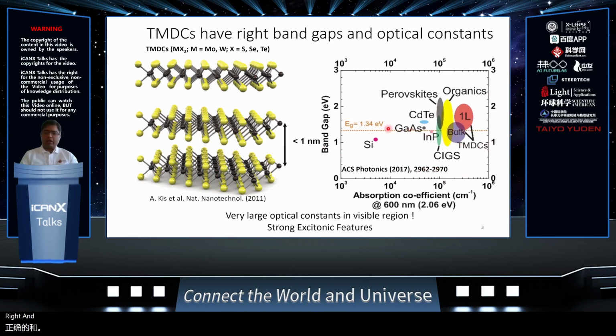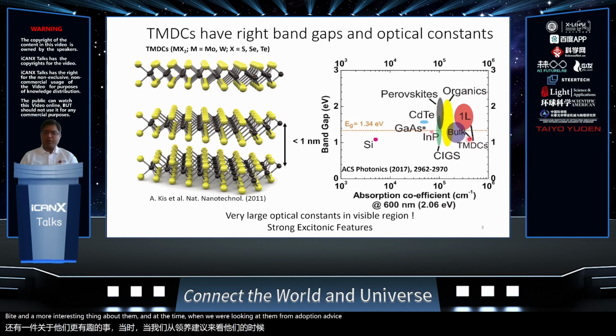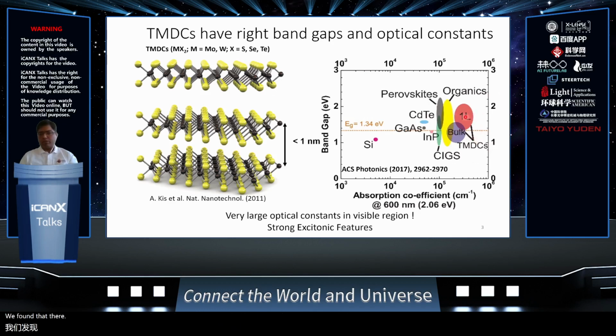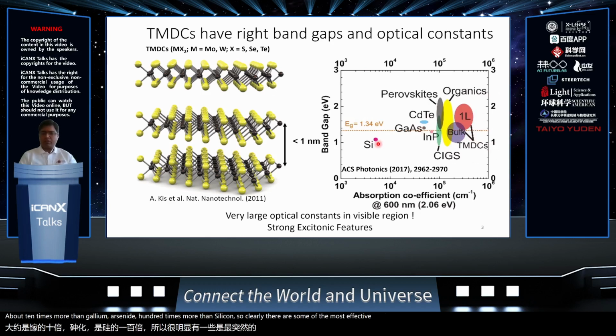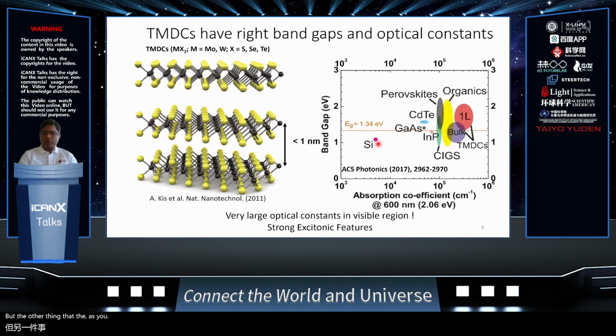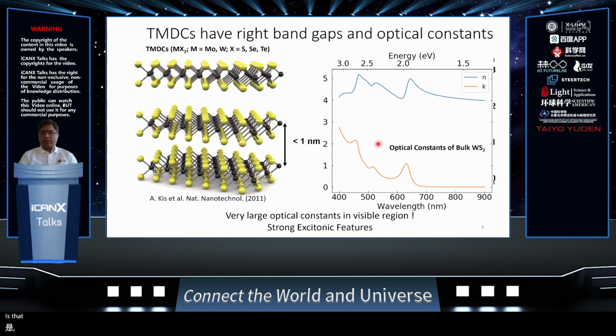The more interesting thing about them, at the time when we were looking at them for absorption device properties, is that we found their absorption coefficients are some of the highest known, about 10 times more than gallium arsenide and 100 times more than silicon. So clearly, they are some of the most absorptive materials we have seen, even more than organics. But the other thing you find as you dig further into the literature is that these materials also confine light extremely well.